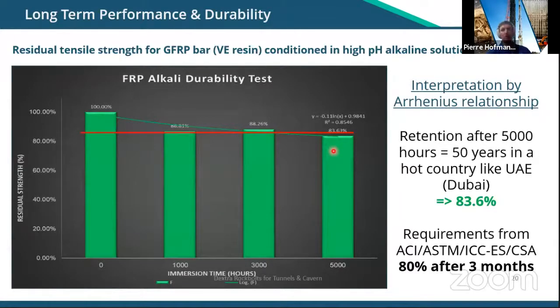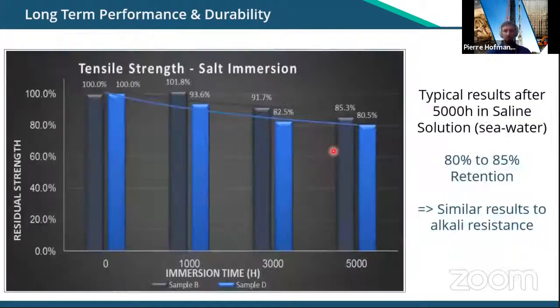So that's really the interesting aspect. We know that steel material would corrode, would degrade, and that would even accelerate, that the concrete might burst and the concrete spalling, etc. The beauty with GFRP is really after initial loss, the reaction is logarithmic and almost zero. I mean, the further loss.